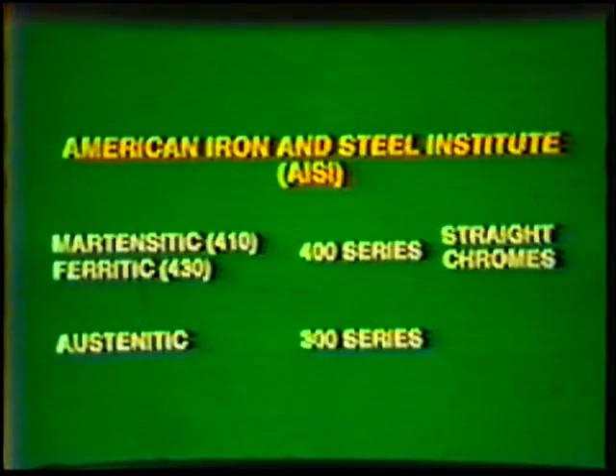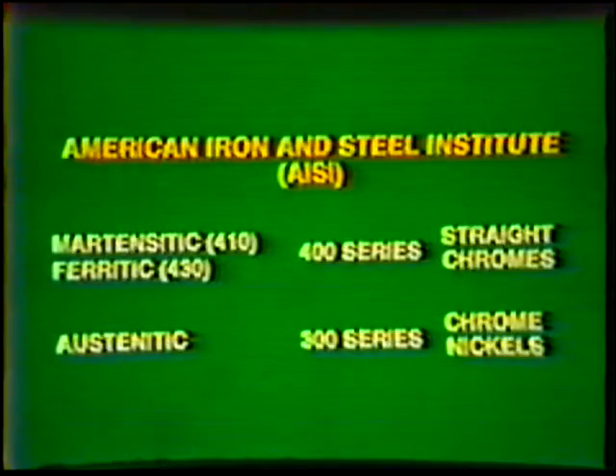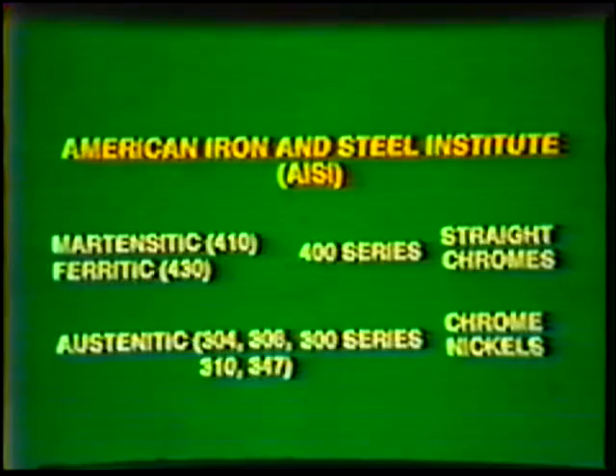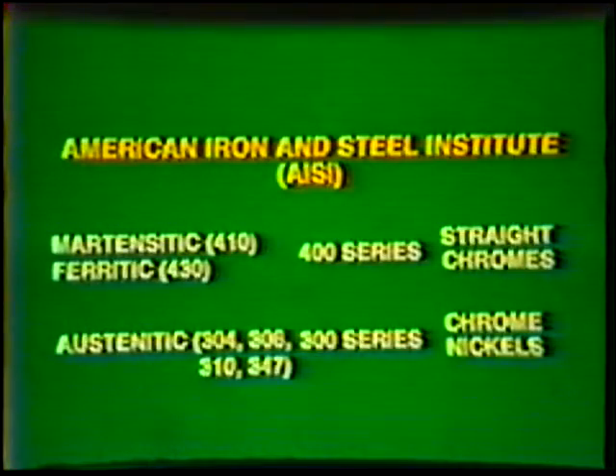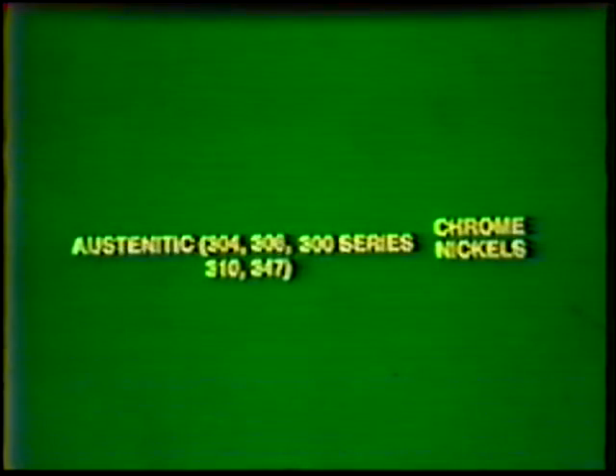The austenitic type stainless steels are designated with a 300 series number. These are called the chrome-nickel stainless steels because of the addition of nickel as an alloying element. Some examples of the austenitic steels are 304, 308, 310, 347, and so on. Sometimes an L is placed after the three-digit designation to indicate a low-carbon content. For instance, a 316L would be an austenitic stainless steel with a carbon content of 0.030% maximum. We will restrict our discussion to the austenitic group, since this series has the best weldability and is the most common type welded.